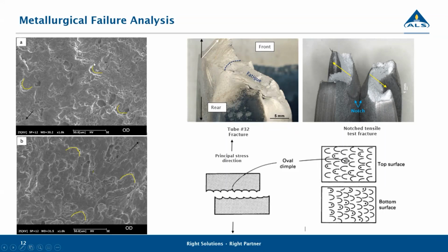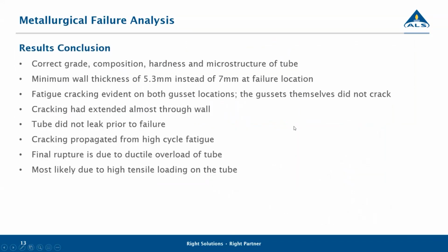If we look at the fracture surface above and below, you get these dimples, and the orientation of these dimples, if you look at the ASM fracture manual, gives you an idea of what happened and which direction the final overload was. So that all confirmed that there was a definite tensile overload that occurred on the last section. We also did a test in our lab where we notched a bar, pulled the notched bar, and looked at the fracture surfaces, which were very similar.